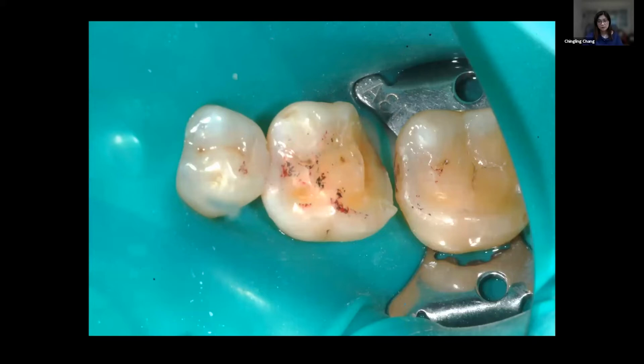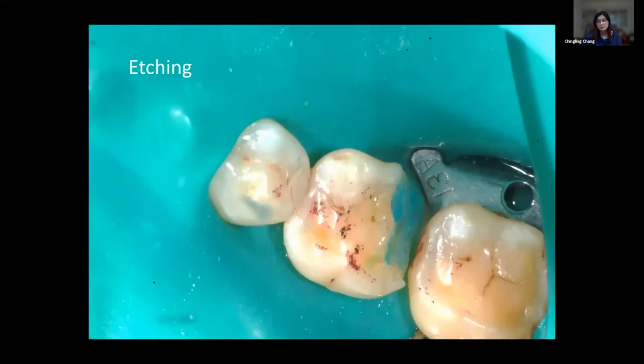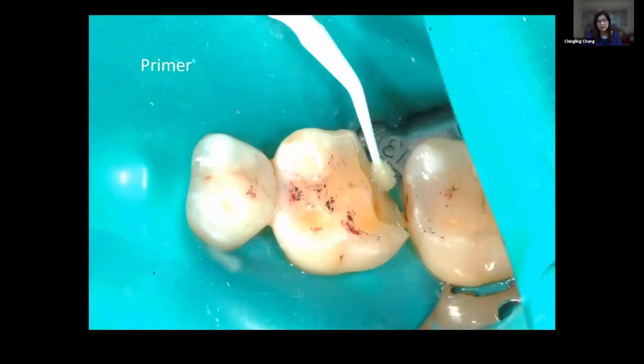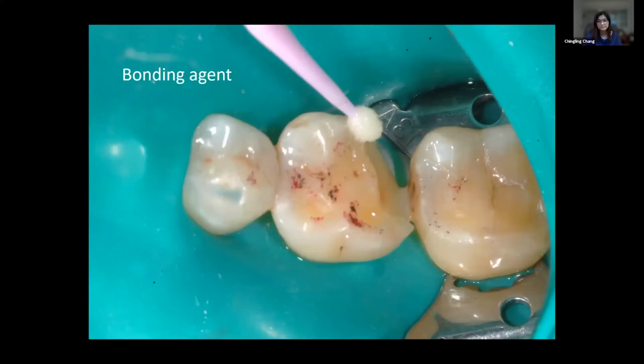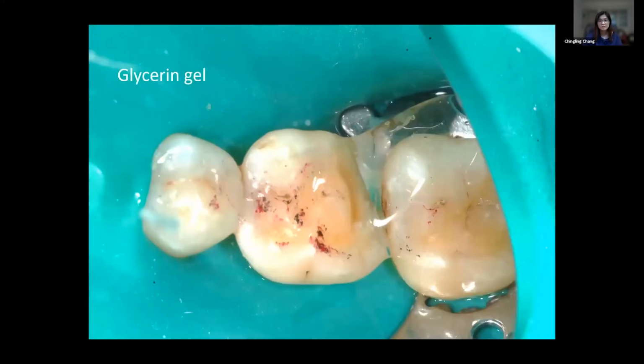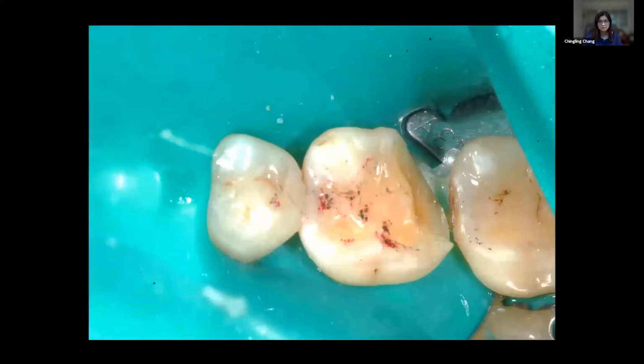So this is a photo showing how to do the immediate dentin sealing. We do the isolation on all the teeth, and we apply the etching agent on the exposed dentin area. Rinse out, then we apply the primer, and we slowly and gently blow dry the primer. And we apply the bonding agent, but we don't really use the air to thin the bonding agent. Then we apply glycerin gel to block the air, and then we do the polymerization. This is after polymerization. We remove the glycerin gel. We can see the extra bonding agent flowing out, and we'll be able to remove it by using a blade or the diamond bur.